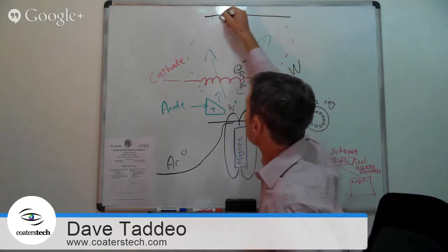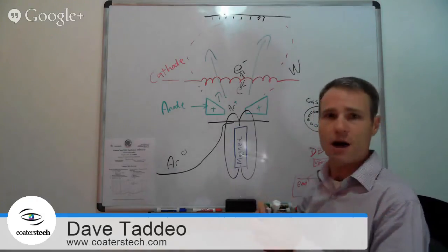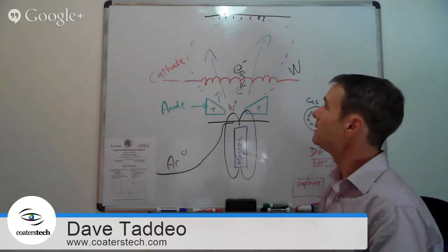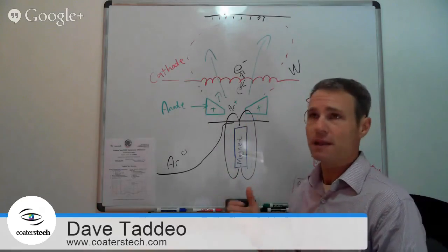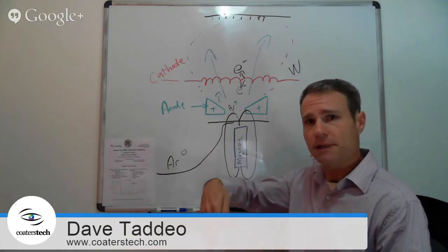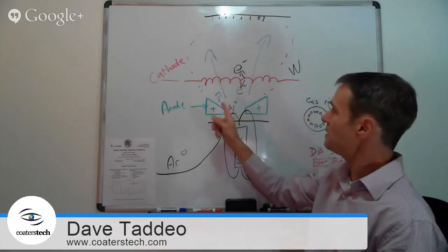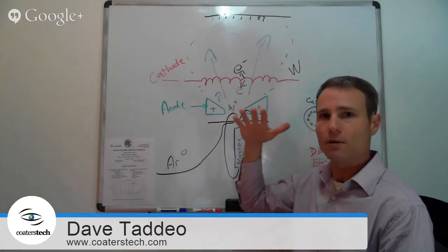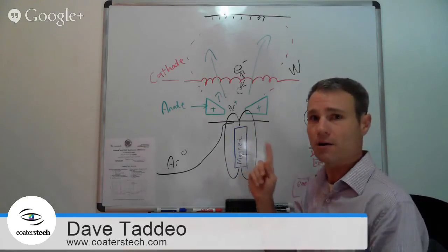So there's some smashing happening here. On a very, very microscopic scale, the substrate is being etched. In particular, with ophthalmic lenses — probably 99-100% of them — are dipped in a lacquer or hard coat to give a scratch-resistant coating. What we want to do in this particular phase is to break the surface tension, or rough up that surface, so that the coating will actually stick to the lacquer, to the hard coating.